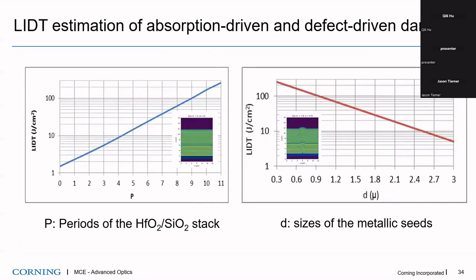So based on that, we can estimate the laser damage threshold as a function of the stack period on the left, without defects. That's purely due to the hafnium silicon multilayer stack, right? So up to 9 periods, you can get around 100 joules per square centimeter. And then on the right is the laser-induced damage threshold as a function of the seed size. That gave us, the larger the seed, the further it reduces the damage threshold, right? So that gave us a sense of where we should control our process, to make it manufacturable, how small the seeds or the defects we care about on the substrate surface need to be.